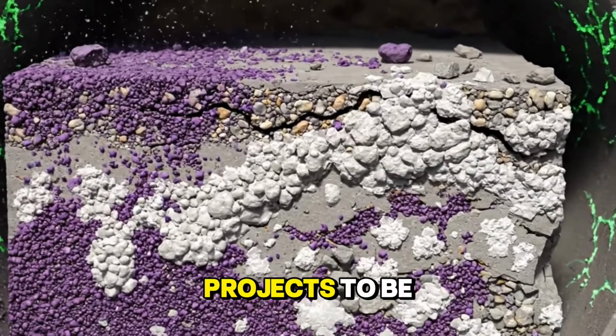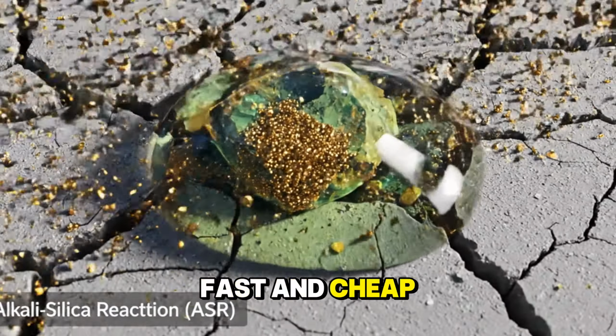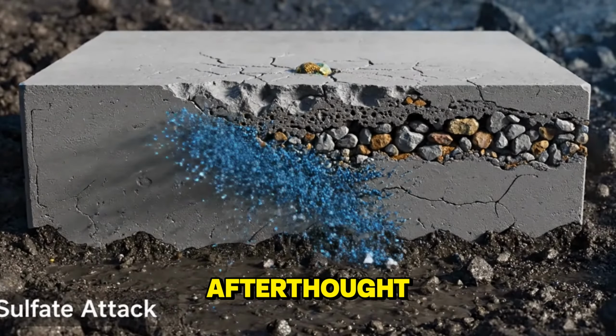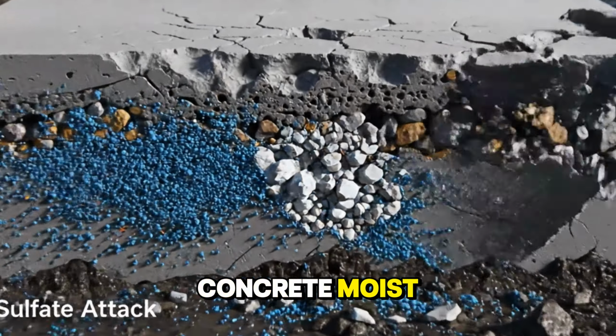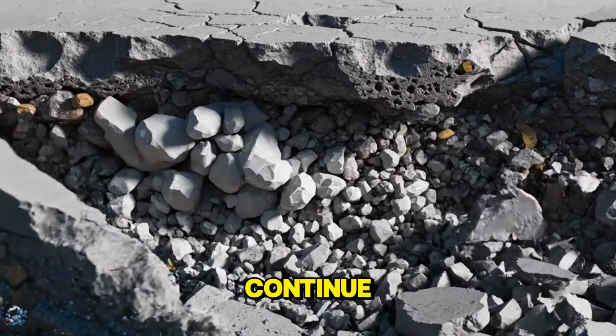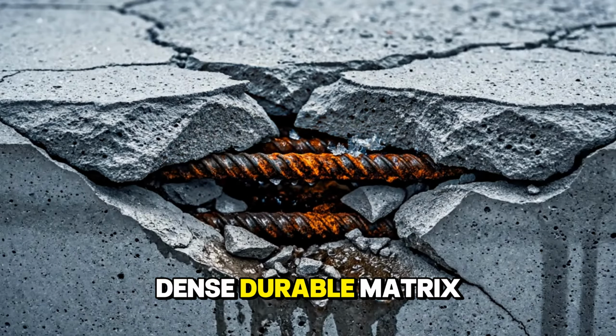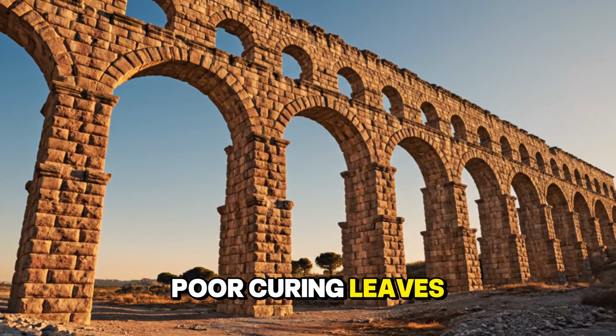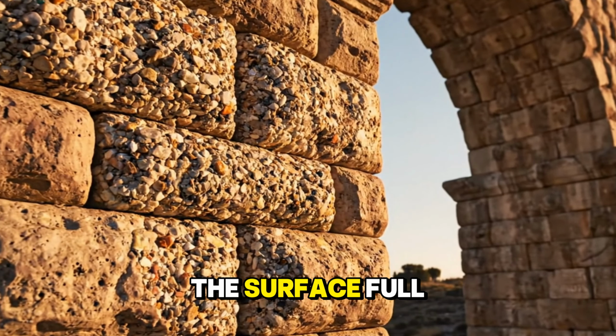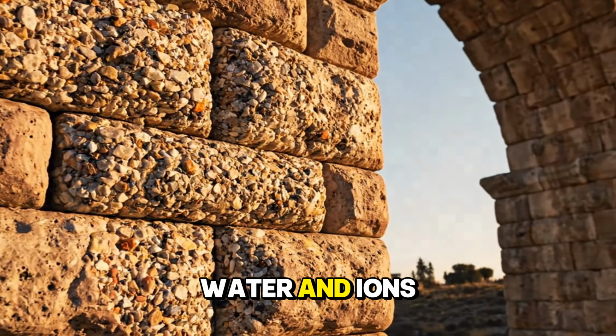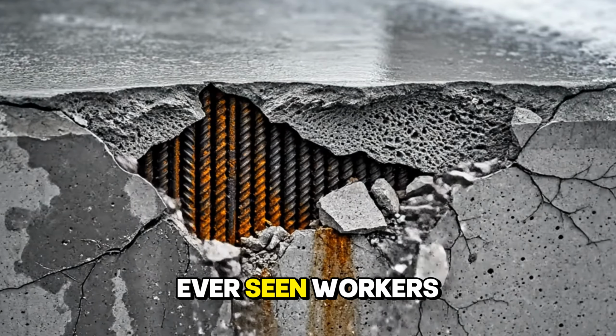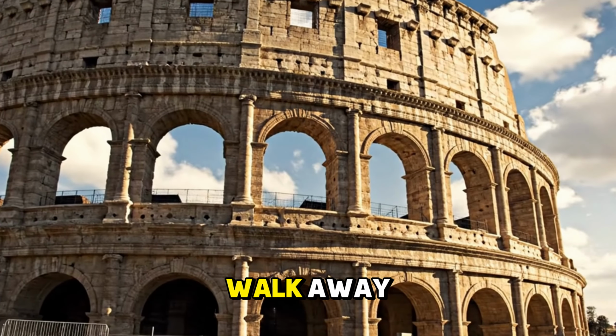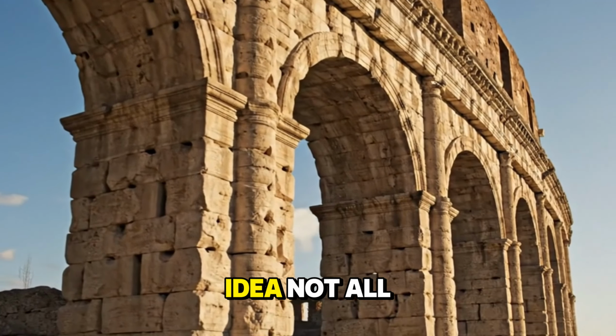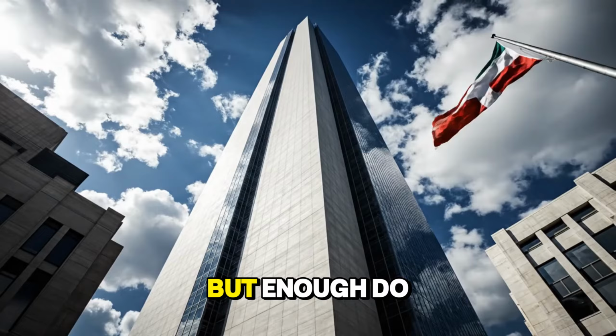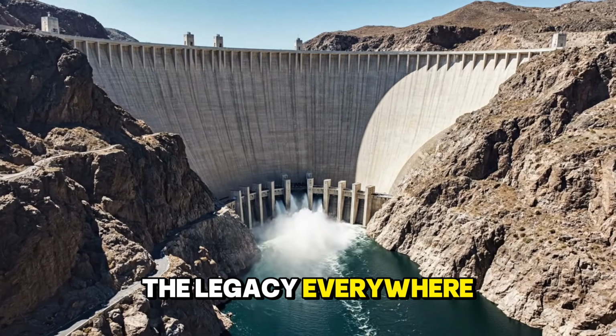Third, we push projects to be thin, fast, and cheap. Curing becomes an afterthought. Good curing keeps concrete moist and warm enough for hydration to continue. That builds a dense, durable matrix. Poor curing leaves a brittle, cracked skin on the surface, full of pathways for water and ions. If you have ever seen workers hose down a slab and then walk away, you get the idea. Not all projects skip curing, but enough do that we see the legacy everywhere.